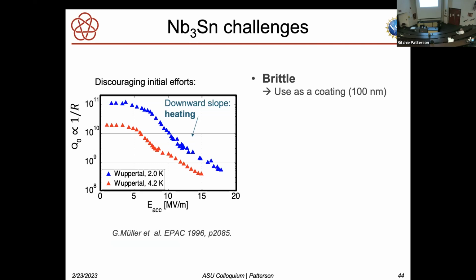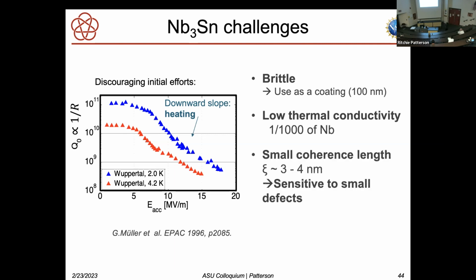There are other problems. Niobium-3 tin is super brittle. You can machine niobium, but there's no way you can machine niobium-3 tin. Instead, people talk about coating it. The fields don't penetrate very deep inside a superconductor. It's maybe 100 nanometers. So you only really need microns of thickness to get the performance. Then it has very poor thermal conductivity. I'll come back to that. That turns out to be a problem. It has small coherence length. That means that you're going to be very sensitive to small defects.